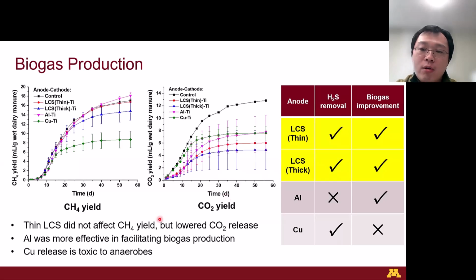Apart from hydrogen sulfide removal, we also examined biogas production on our collaborating farm. The manure in the transition pit will be pumped into the anaerobic digester for further organics decomposition and biogas generation. Therefore, we hope that the BEC treatment can improve the biogas generation or at least not negatively affect the subsequent AD process. So our findings revealed that the thin low carbon steel did not affect the methane yield, but it lowers the COD and the carbon dioxide release.